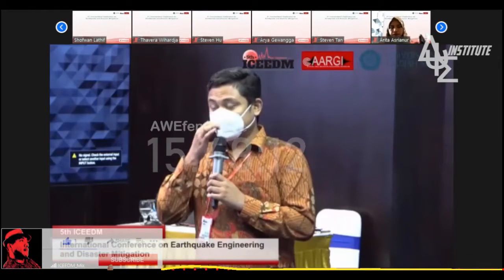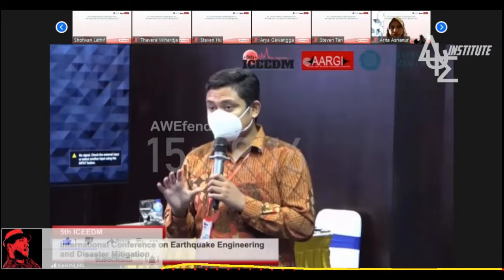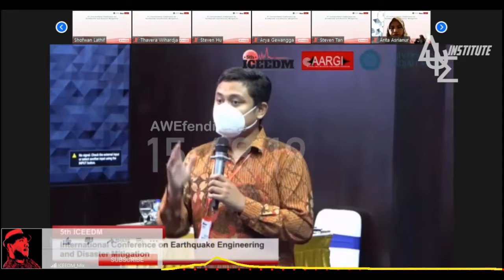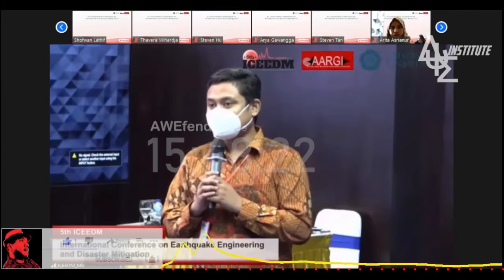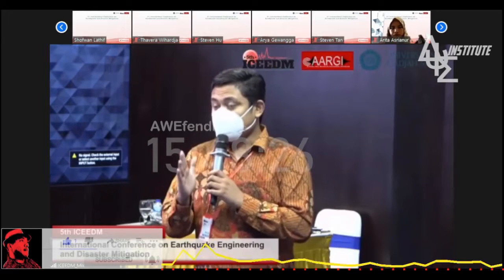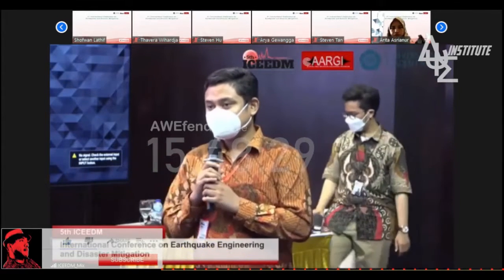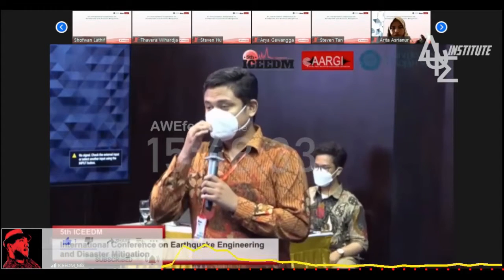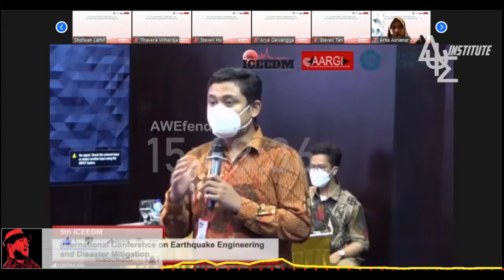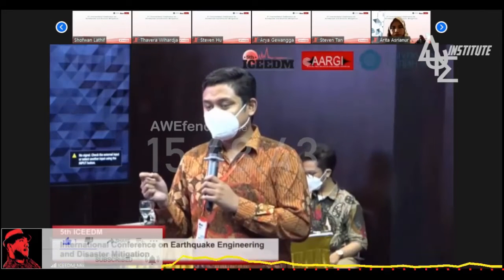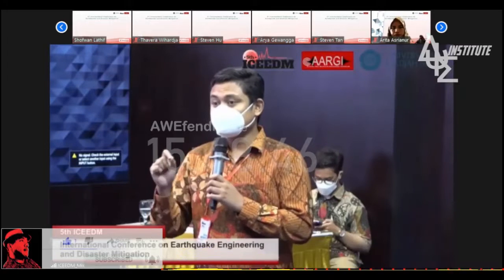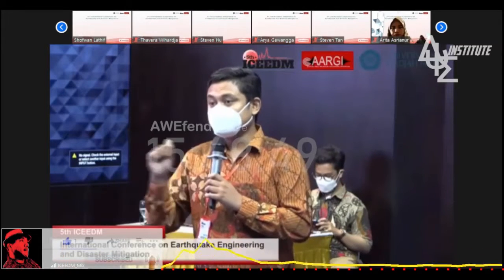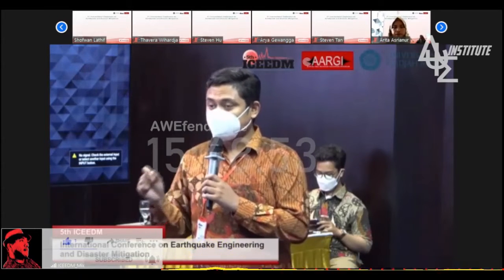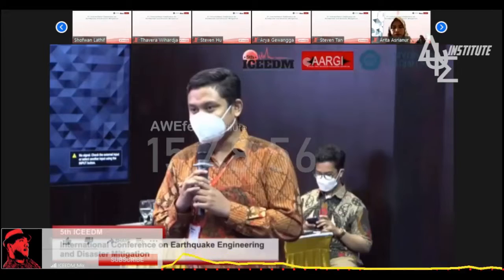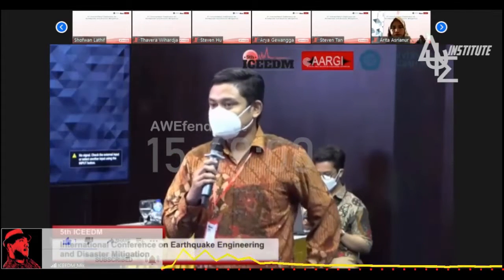But in ECC, at the end of the test, we see some big opening cracks, localized cracks at the interface only, something like that. It's towards the plastic region of the beams. For the second question about the model, because we adopted 3D modeling, we use discrete representation for the rebar. So it's not smeared, but followed what we did during casting. But for the concrete, we use a fixed smeared concrete model. I hope it answers all the questions that you raised.